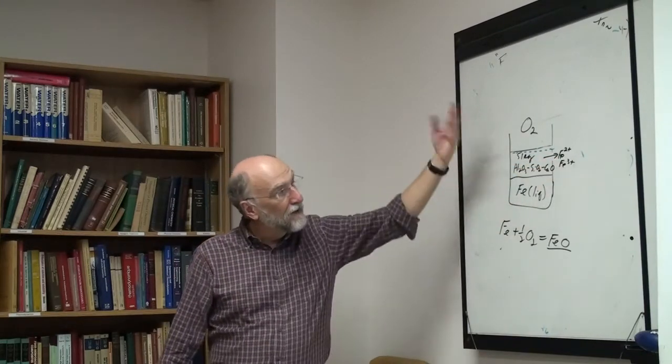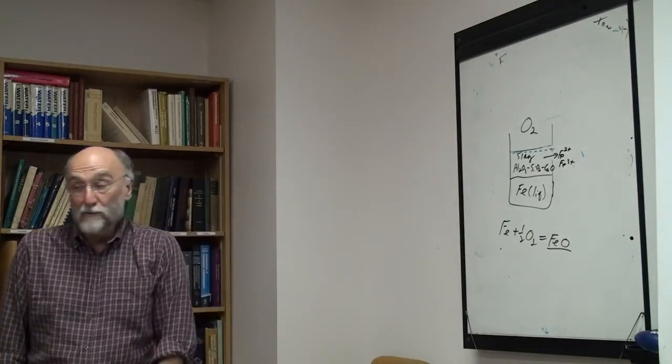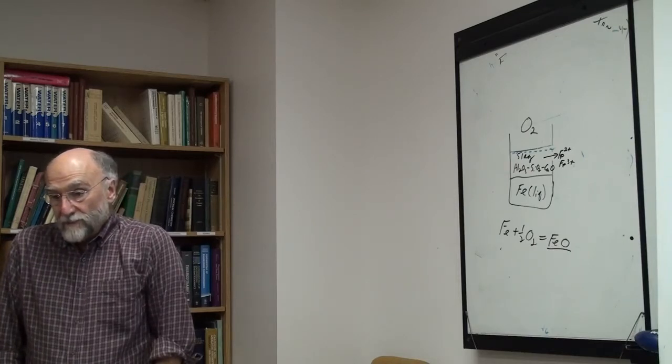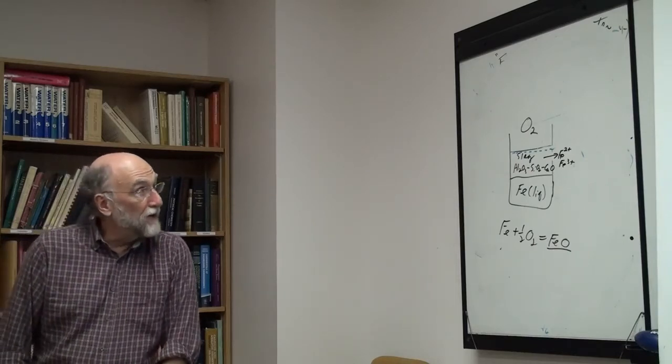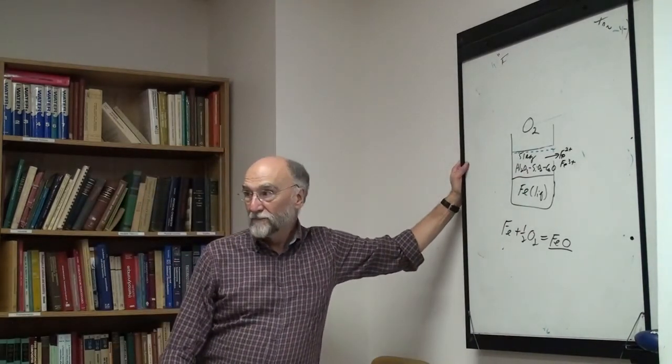But the minute you put in something like iron or chrome or manganese, then the slag is an ionic and electronic conductor, and the thing goes much faster, because the electrons or positive charge will move one way or the other through the slag.